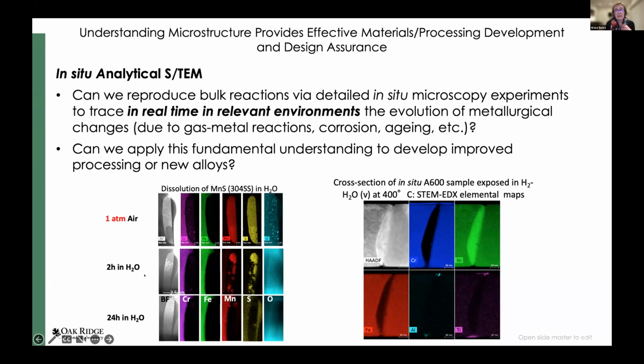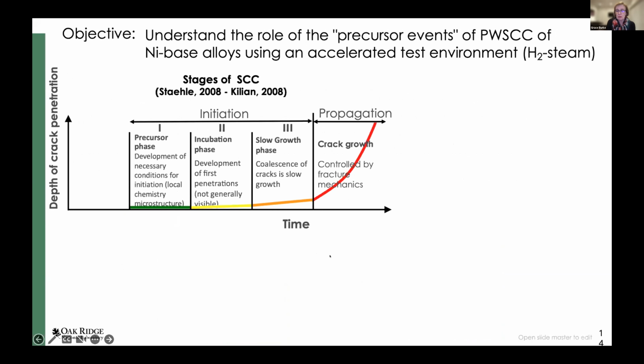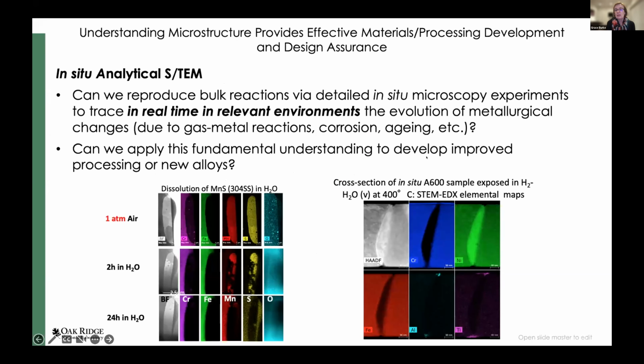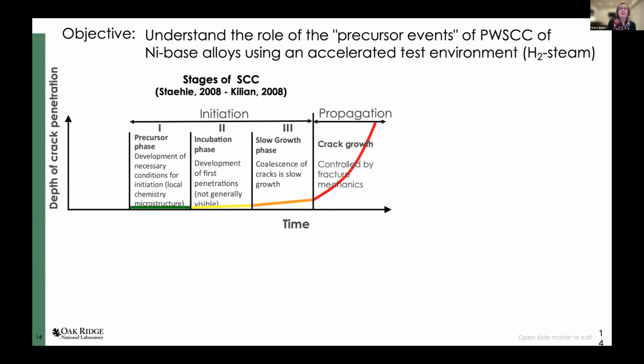So these are taken in the microscope in the cells. You can see there's water present because of the oxygen that we're able to pick up as well while these are dissolving. On the other hand, we've got cross-sections of some alloy 600 specimens that have been exposed, and you're going to see more about those later and why that's important.